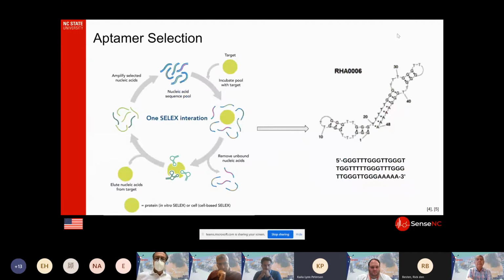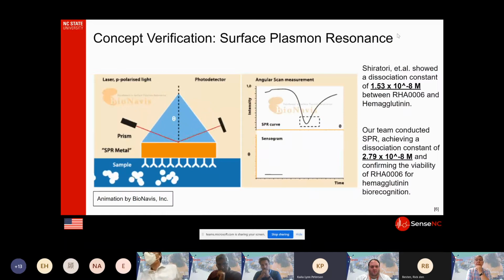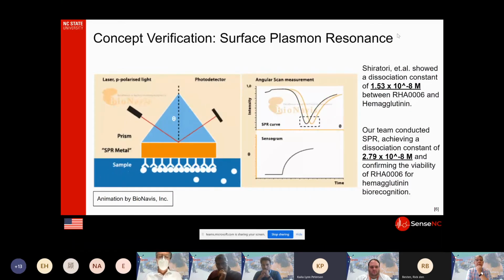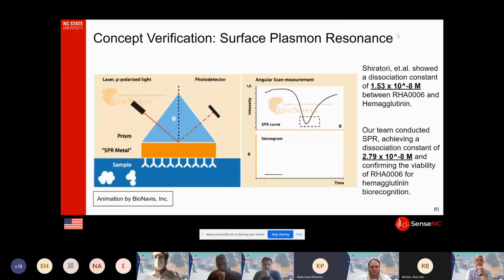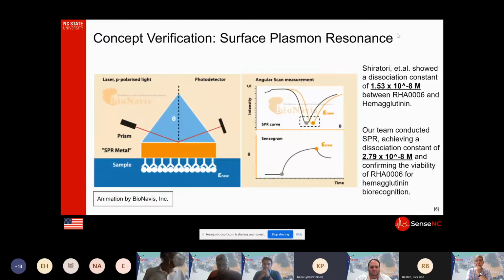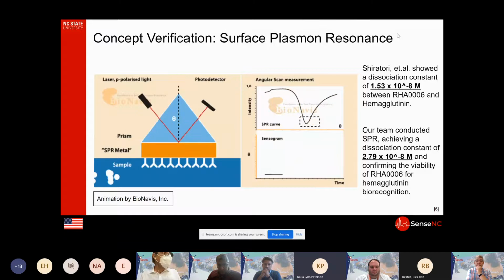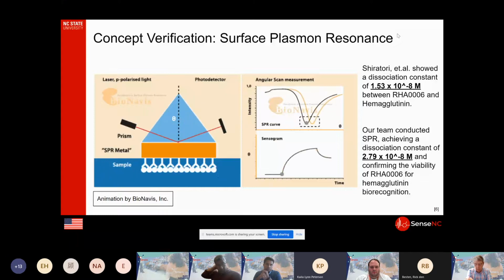So the first step in this process required our team to select an aptamer with a high affinity for hemagglutinin. We chose an aptamer from the literature, which was identified via SELEX, with a reported dissociation constant of 15.3 nanomolar. Our team then verified this affinity of the selected aptamer via surface plasmon resonance, or SPR, the details of which can be seen here. We measured a binding constant of 27.9 nanomolar, which is highly comparable to that established in literature, thus confirming the viability of our aptamer for hemagglutinin biorecognition. This binding constant is also significant because it indicates a potential for successful detection at biologically relevant levels, which is about 500 molecules of hemagglutinin per viral particle of H1N1.